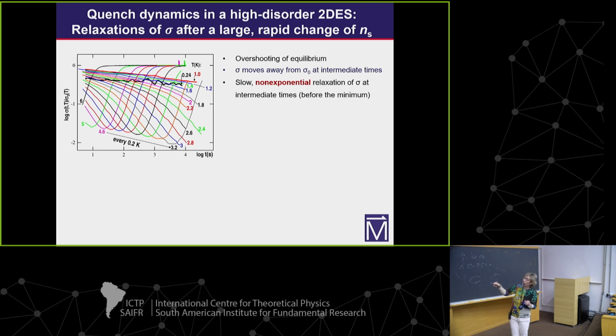So if we fix temperature, as I showed you previously, conductivity decreases, goes even farther away from equilibrium, and then eventually it will reach this equilibrium value. As you reduce the temperature, this process becomes slower. This minimum shifts to longer and longer times.